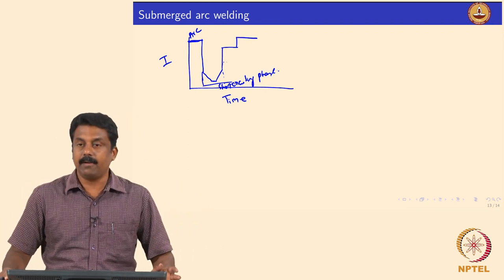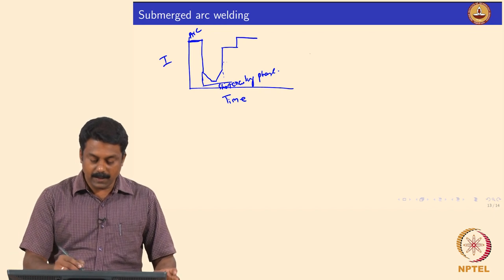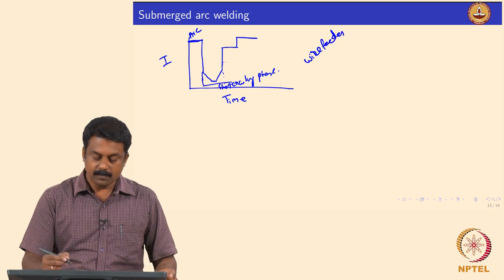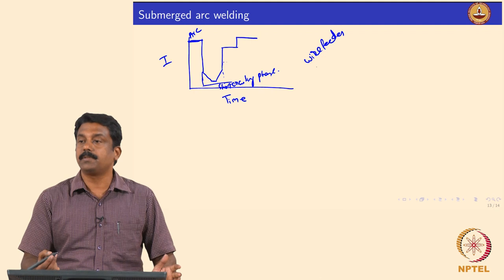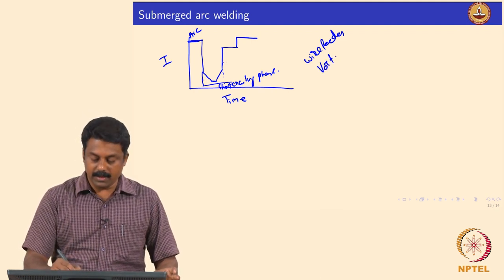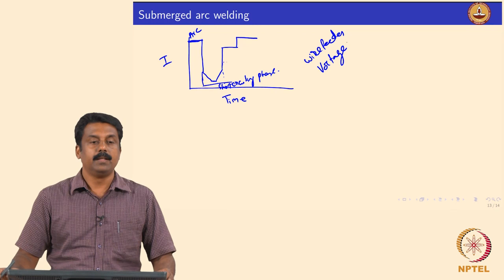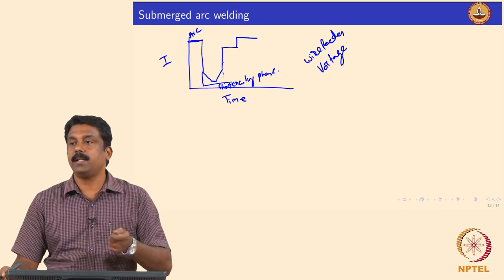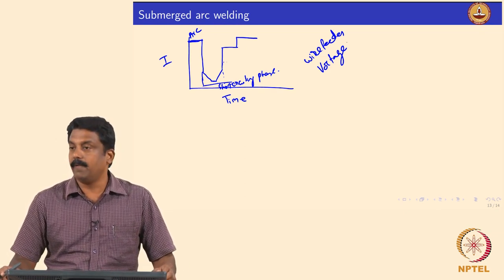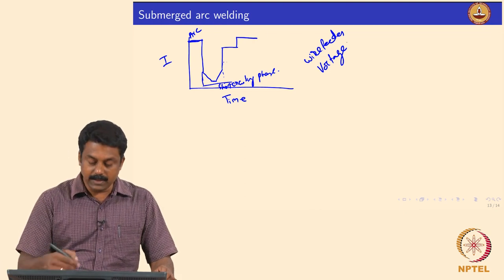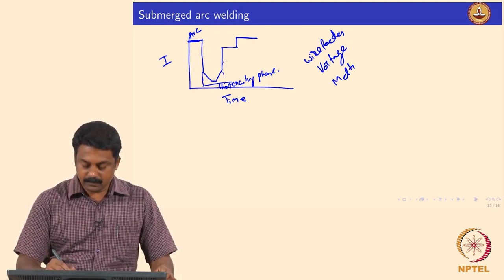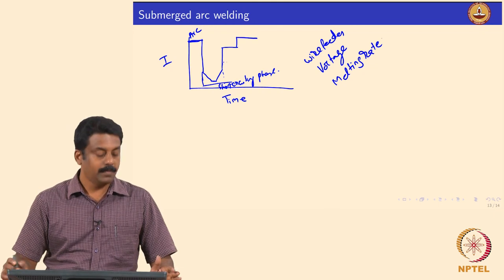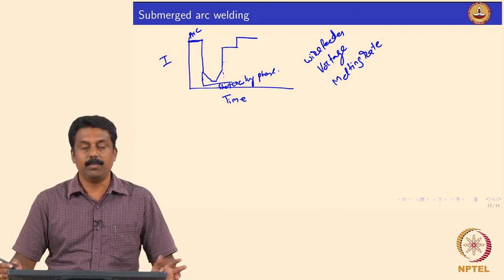So now we will have to make our system as smart as possible. We need control over the wire feeder, and we also need to measure the short circuiting event — so we need a voltage sensor. Voltage has to be measured so that the moment short circuiting happens, we make the current go to zero or a low level. We then have to do calculations about the melting rate so that we know when to retract and when to send the wire towards the weld pool.